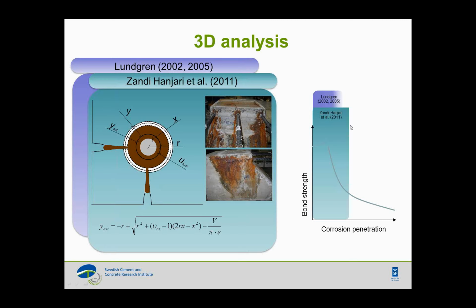But still we cannot go all the way, because at one point the cracks would be so large and the cracks will be connected to each other, and we come to a delamination plane, and that cannot be described with regular finite element analysis. So what we do is that actually we have written a script in MATLAB which is coupled to Diana now.